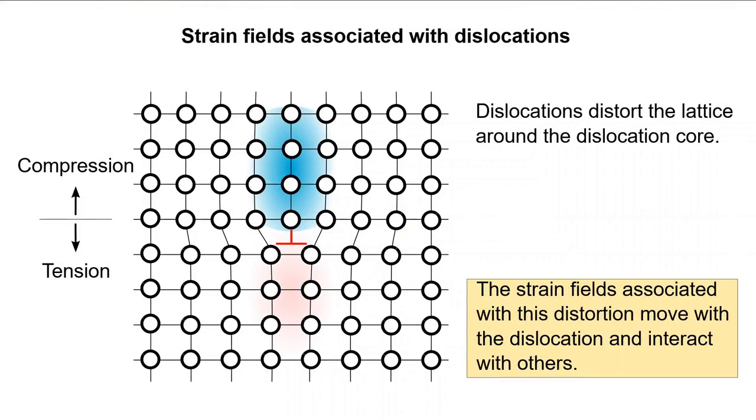I have already described an edge dislocation and the method by which it moves. Due to the extra plane of atoms, there is a local compressive strain field on the side of the dislocation which contains the extra half plane of atoms. A balancing tensile strain field occurs immediately below this. It is compressive at the top as the mean distance of atoms here are marginally closer than at the bottom, where they are further apart.